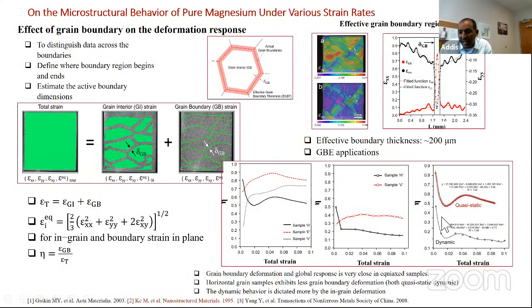We also try to understand how the grains actually participate in the deformation mechanics. One thing we try to do is separate the strain on the grain boundaries from the strain inside the grains. First we try to identify the grain boundaries, and for that we use digital image correlation again. We use two strains and separate the position where the strains change. You can see this is where we show in the epsilon-xx and epsilon-yy, and literally you can see there is a big jump where the strains are changing, and that's where we found the grain boundary.